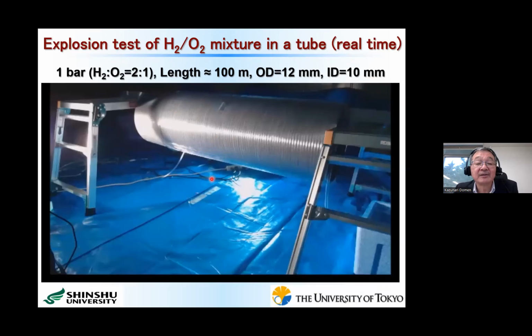And the inside of this tube was filled with hydrogen and oxygen in a 2-to-1 ratio and saturated water vapor. Here we have a Tesla coil to cause the explosion. And the outlet is here. It goes into the water layer at 5 centimeter depth.